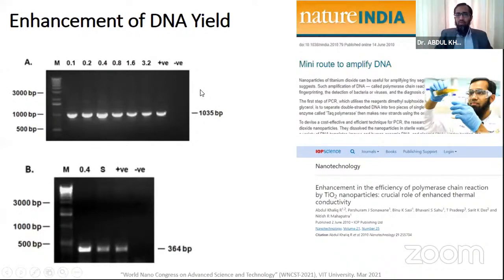Secondly, some people argue nanoparticles do not necessarily have an effect. The effect of conductivity of nanoparticles may not have a direct effect. Rather, it could be some other mechanism, such as DNA binding along the nanomaterial, or the polymerase getting in contact with the material, and as a result augmenting the PCR. To defeat those kinds of arguments, we took out the supernatant of the nanoparticles, and to see if there are any chemical reactions, we did a PCR with only the supernatant of the nanoparticle. What we found is there is literally no impact of the particle chemistry on the PCR reaction.